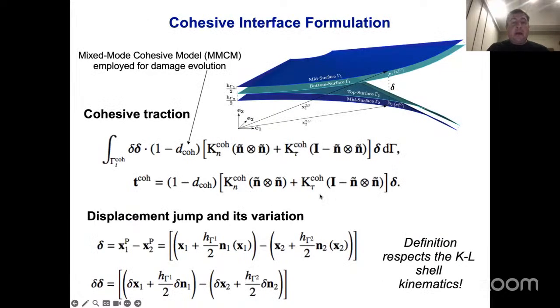It's multiplied by a stiffness tensor, which makes use of different stiffness values in the normal and tangential directions, and it's multiplied by 1 minus d cohesive, where d is a cohesive damage variable. The damage variable is evolved according, as I said, to a mixed-mode cohesive damage law. The key thing here is that the displacement jump, or separation, and its variation that's needed, makes use of a definition that respects the kinematics of the Kirchhoff shells here.